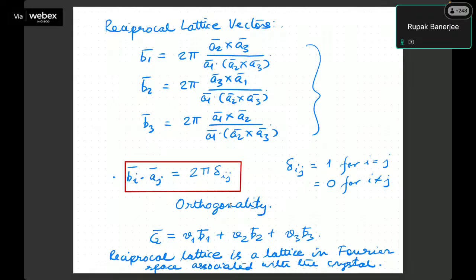It turns out that we can, and we have all learned about this in our vector algebra chapters, I think class 10 or 11, wherever this is. So for any lattice vectors or set of lattice vectors, if there are a1, a2, a3, you can create another set of lattice vectors b1, b2, b3 just by using these formulas. For b1, it is a2 cross a3 by a1 dot a2 cross a3. For b2, it is a3 cross a1, and for b3, it is a1 cross a2, right? So I now know that if I am sure about my real space lattice vectors, I can create reciprocal lattice vectors b1, b2, b3, in which the reciprocal lattice is defined by the G vector.